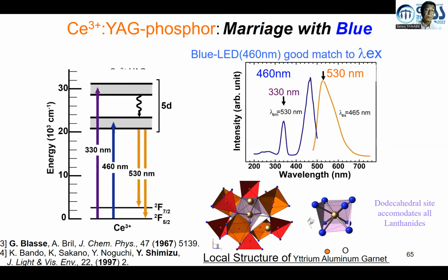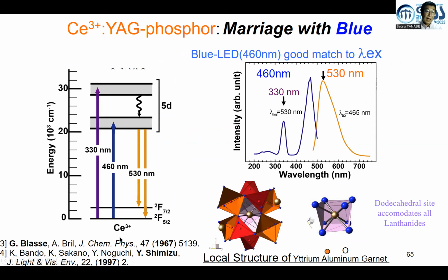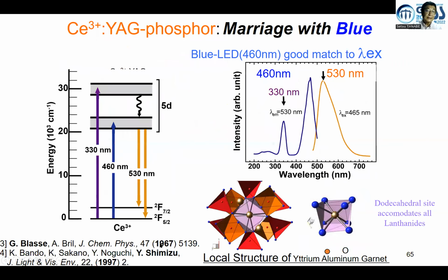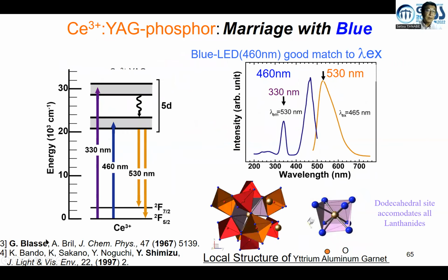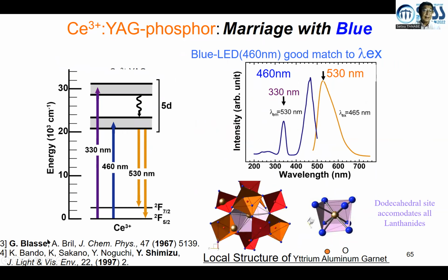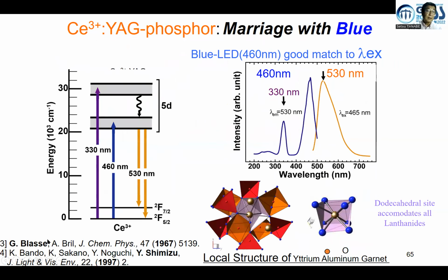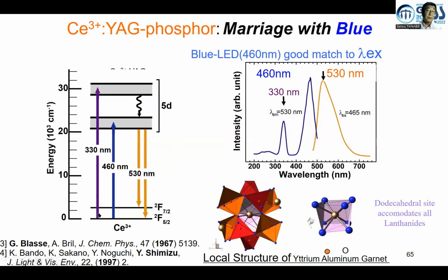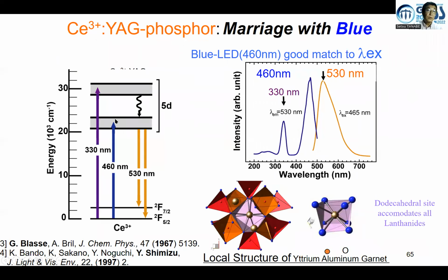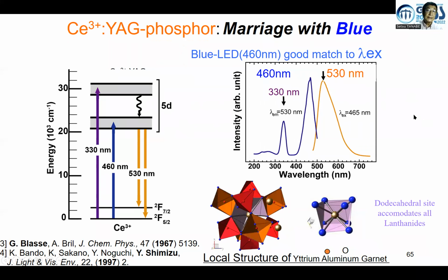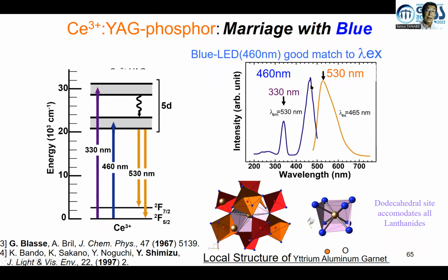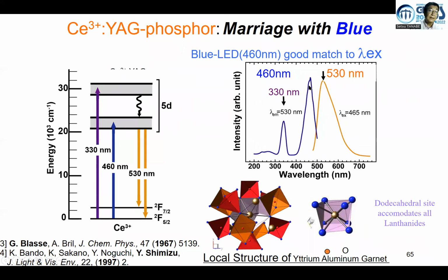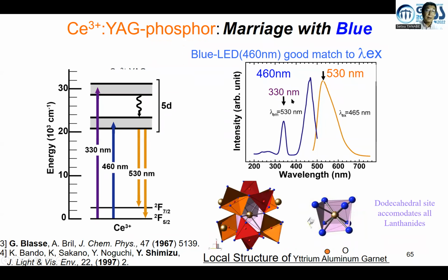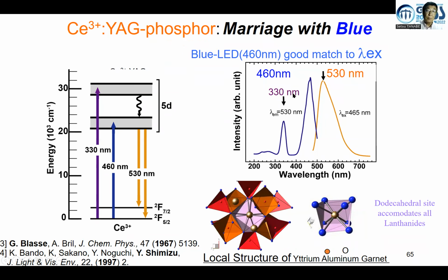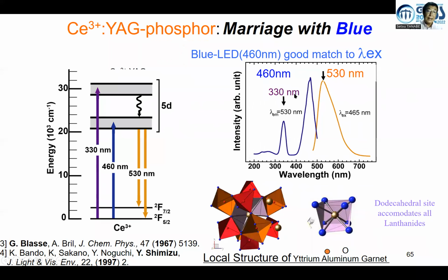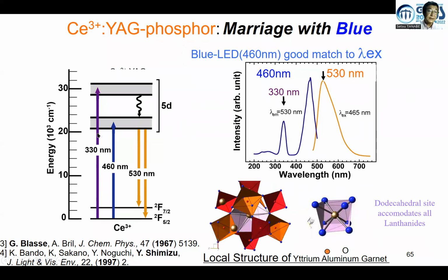And YAG-cerium was actually known in the 1960s by Professor Blasse, Utrecht University. He invented YAG-cerium yellow phosphor, utilizing very strong blue absorption. This is an excitation spectrum peaking at 460 nanometers due to the 4f-5d transition, which is Laporte allowed. So very large absorption cross-section.